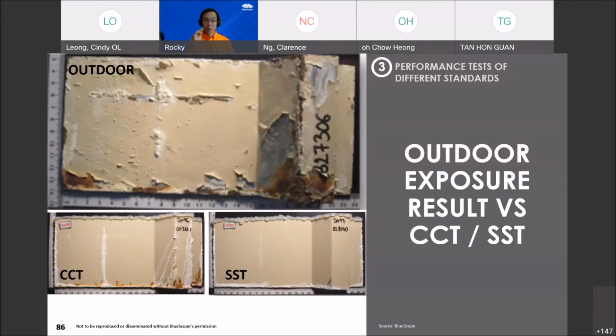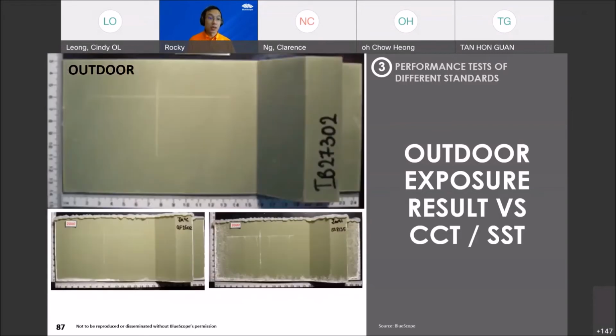So this shows that not often does a salt spray test show a much more severe result. And the intention here is not to look at the worst result out of the simulated tests, rather which one is more realistic to the actual. And this is another one where salt spray test again seems like it is yielding worse results, but in cyclic corrosion and outdoor, it doesn't seem like the case.